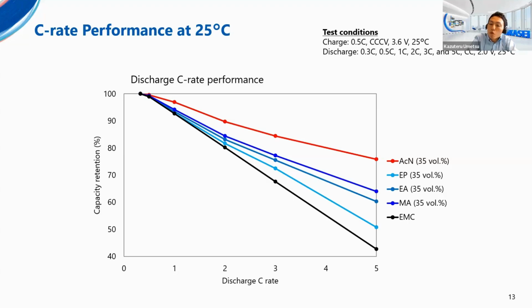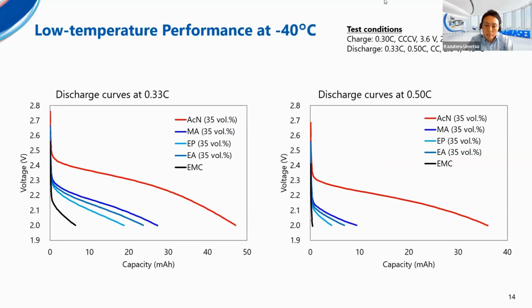Acetonitrile showed the best performance among these solvents, and the esters were better than EMC. Similar to the trend in ionic conductivity, among the esters, MA was the best, followed by EA and EP. Acetonitrile showed the best performance at 25 degrees C, but its advantage was further enhanced at the extremely low temperature of -40 degrees C. These graphs are discharge curves at 0.33 C and 0.5 C from 3.6 volt to 2 volt. All esters improved low temperature performance, but acetonitrile even more.